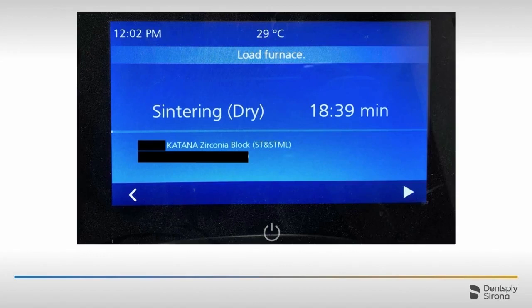And so Katana came out with a very novel and very great sintering cycle that allows you to sinter their material in 18 minutes and 39 seconds. Now, traditionally, a translucent zirconia would take 9 hours to sinter. And the fact that they were able to fabricate their powders specifically with the purpose to fast sinter has made chairside translucent zirconia a reality.